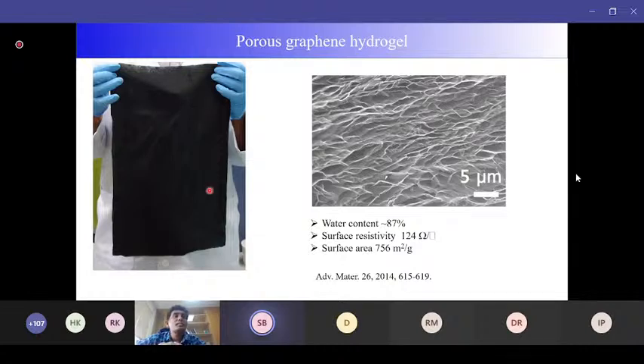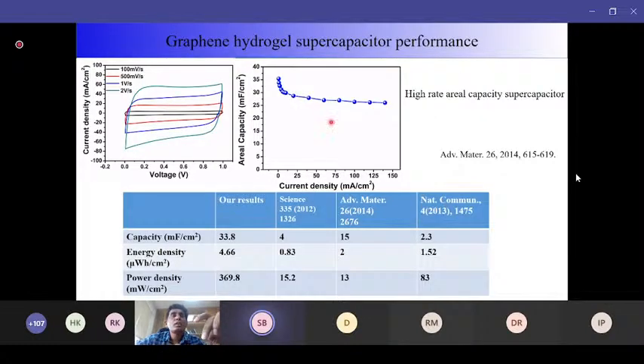You can imagine that this is a very big structure where we started with graphene, but the graphene sheets are of some microns in lateral size. And as you can see from the cross-sectional SEM image, this is a really highly porous structure. So these are the graphene sheets, and there are lots of pores, and it stably binds the water. The water content is around 87% of its weight, and it has a good conductivity. It has a very high surface area. So as I already emphasized, these kinds of systems which have no binder and are porous and highly conducting structures are good for supercapacitive performance.